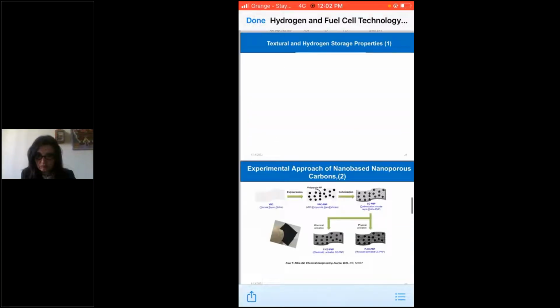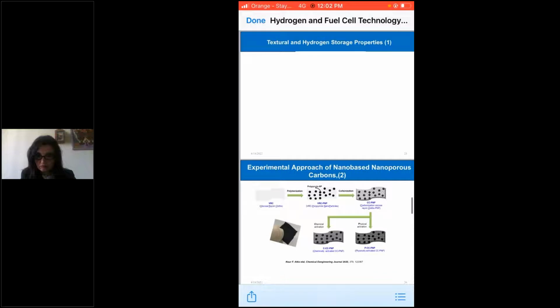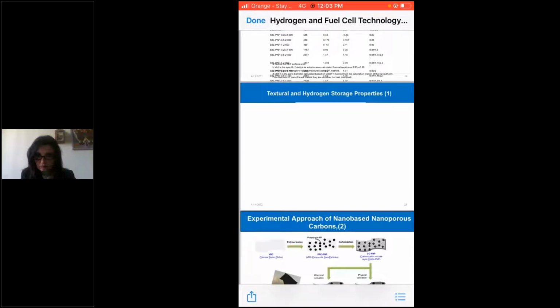The hydrogen uptake is very important. We get around 6 weight percent, and also around 0.3 weight percent at room temperature. This is quite good, especially for carbon materials, and we are trying right now to modify it using some benzene and other materials to improve that value.